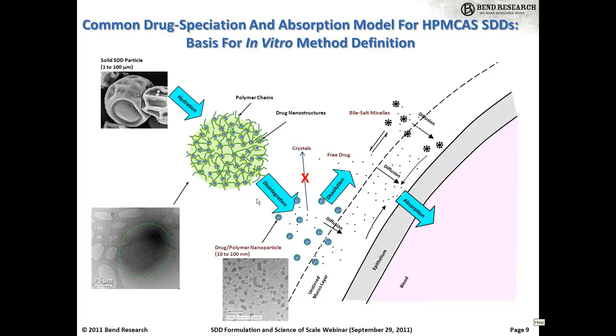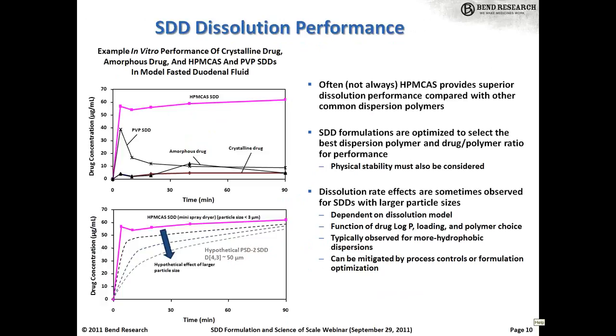And of course, the idea is that you have higher solubility for an amorphous form than for the crystalline form. So as such, you have increased free drug relative to what you have for crystals. And importantly, when done properly in terms of selection of the polymer and the drug-polymer ratio, you can prevent crystallization back out of that supersaturated solution. That's where the drug-polymer interactions in the solution state become particularly important. And again, often but not always, that's where HPMCAS particularly shines. I should say that's one model for the dissolution performance that we often see, but not always.